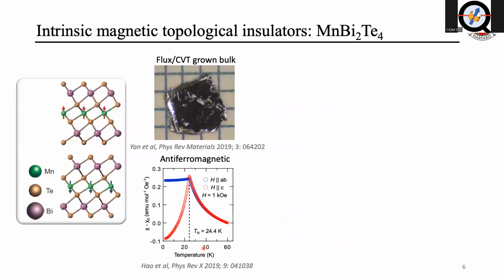Okay, so then the recent discovery in intrinsic magnetic topological insulators, as represented by manganese bismuth telluride, provides a promising platform. So in the magnetic bismuth telluride, the manganese atoms, as illustrated here, form a well-ordered lattice, and they couple ferromagnetically within the septuple layer and antiferromagnetically with the adjacent septuple layer.